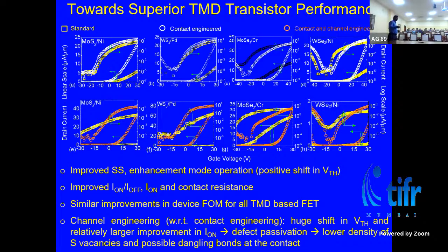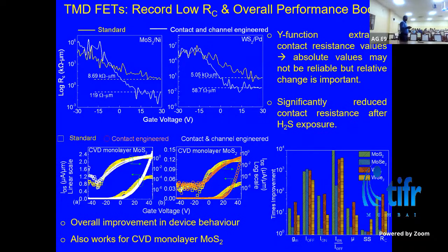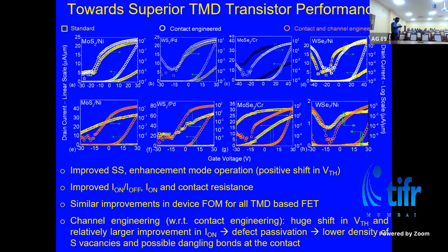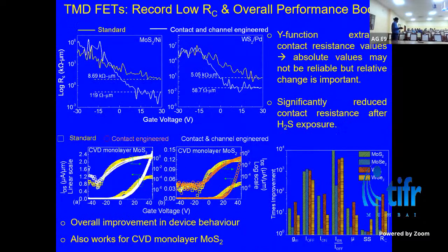Right. So when we do that, we have increased current, right? In one case we compare with both contact and channel passivation. In the other case, we compare only with the contact. So you see a significant improvement in the current for all the different TMDs, no matter which one you choose, whether you take MoS2, WS2, MoSe2, or WSe2. In all cases, we have this improvement in the current. We tested this for CVD material as well, and even for CVD material, the technique works. This was a few layer, and this was monolayer. So the same method works for monolayer as well.